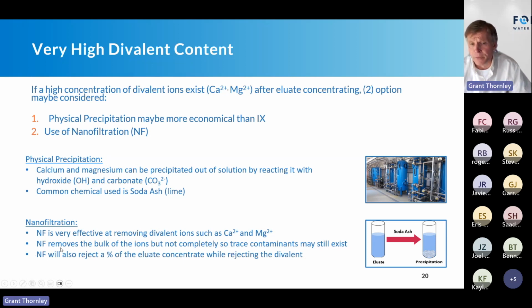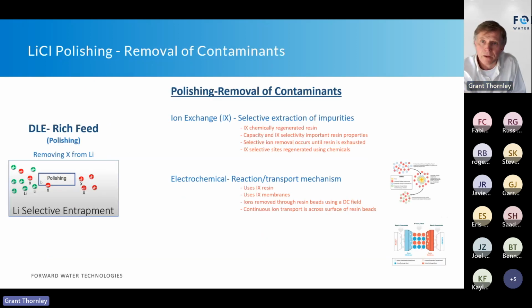But the other component from NF is that it does reject a percentage of the eluate or the concentrate. So not only will it get rid of those divalents, which is great, that's the objective, but you may also lose some of the eluate, which contains lithium. So that needs to be balanced significantly on the economics. It needs to be really modeled out to see if the economics and use of nanofiltration can be justified.